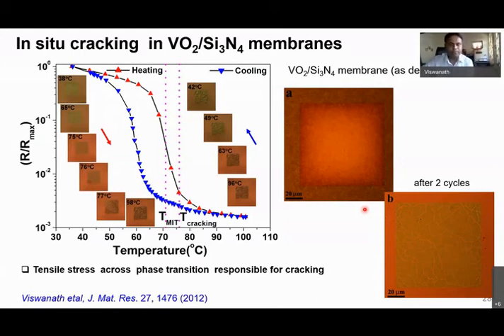Yeah, so I was about to ask, in that case, they would see twin boundaries, right, to accommodate the deformation, whatever the strains. Correct. And how much is the strain difference? Volume difference? Again, the volume difference, as per the literature, starting from neutron diffraction to many other measurements, also scatters. There is a value varying from 0.3 to 0.55% of volume change.